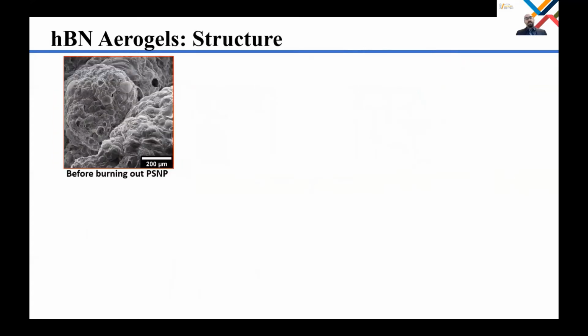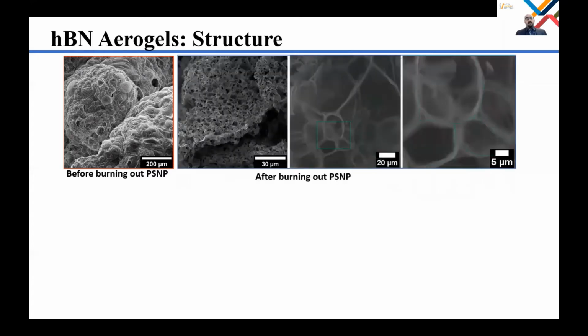In addition to the spectroscopic characterization, we used SEM and TEM microscopic characterization to understand the morphology of BN aerogels. This SEM image shows the BN polystyrene composite before burning out the polystyrene nanoparticles. And the structure, as you see in the SEM image, is assemblies of bubble-like structures. The structure of the BN aerogel after burning out the polystyrene nanoparticles is a highly porous and interconnected cellular architecture with nearly spherical pore structures.